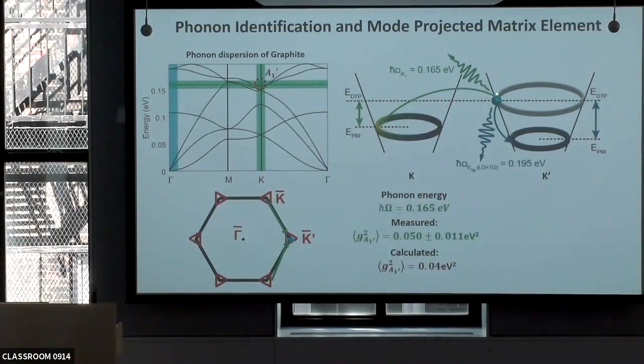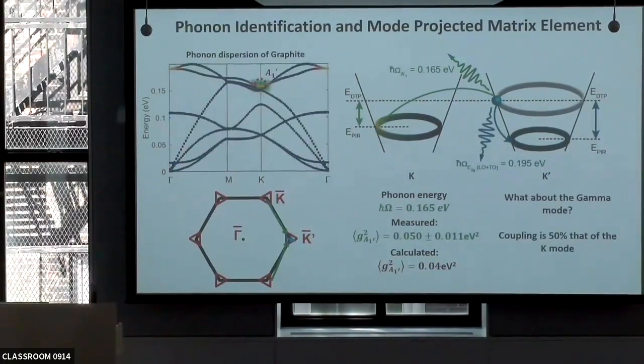Of course, you can also see relaxation going down vertically almost through a gamma mode. In fact, if you look at electron-phonon calculations that take into account all possible scattering channels to all possible states, the two modes seem to be both strong, the K mode and the gamma mode. But when you do a calculation in the same way, you figure out that the coupling is only 50% of what you see from the K mode. So in the end, we don't see that quantity in the peak, although it may be underlying some of the structure, but we are not able to pinpoint that.